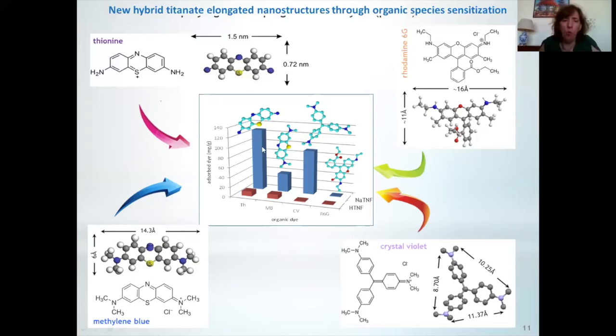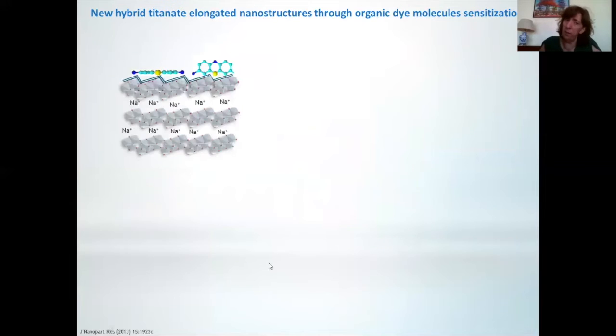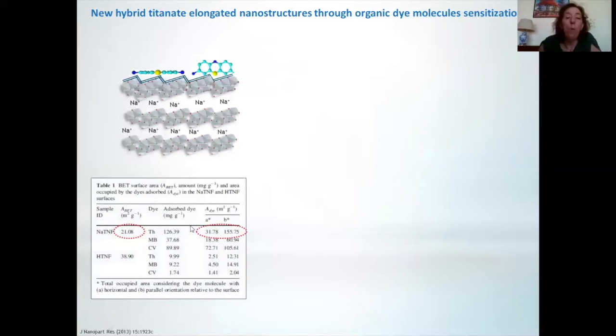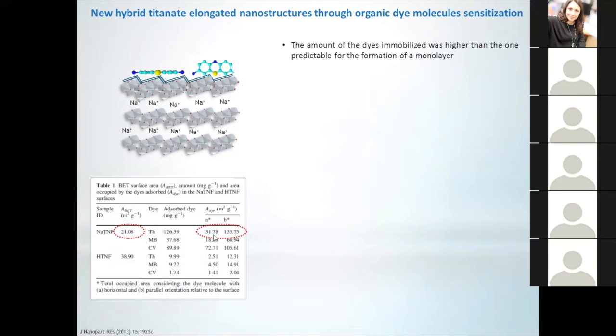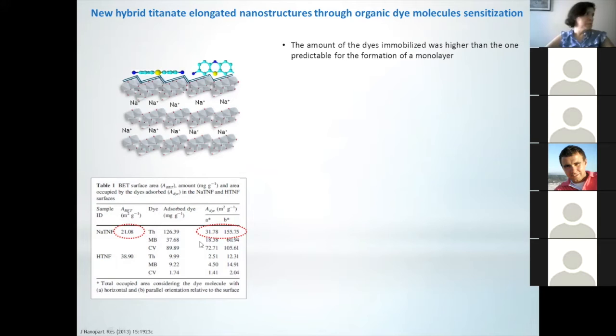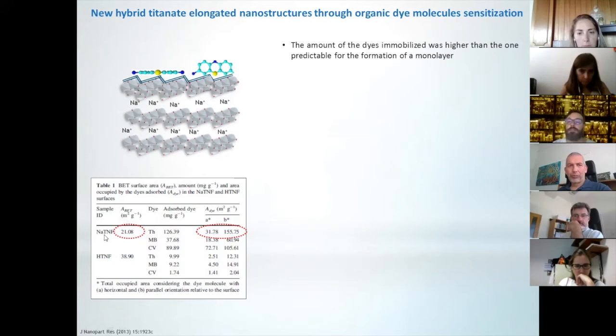So, how about this? Where are these species? Are they on the surface, or is there the possibility that they are in the interlayers? So we decided to study this possibility, and we decided to make some calculations, trying to put all the dyes that were immobilized in the structure. We put them on the surface, first in a horizontal orientation, like this one, or in a 90 degrees relation to the surface. We made the calculations, and in fact, we needed these surfaces that are much bigger than the one that I have in my material.